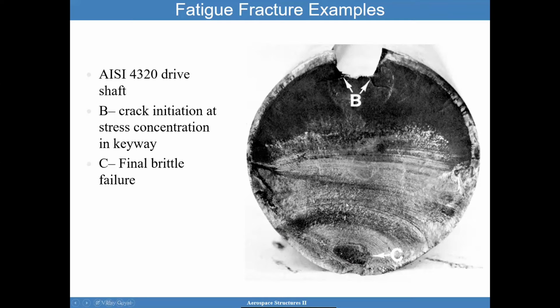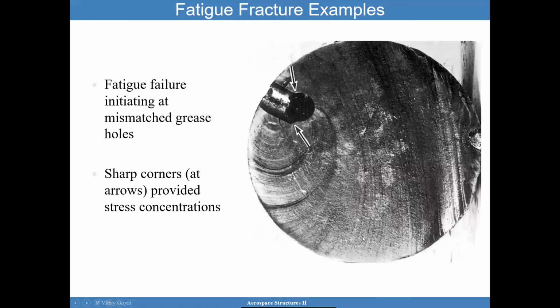But I want to point out that sometimes it's not apparent. In this example, a crack initiated at this stress concentration, propagated, and they had a final brittle failure here at the very end. You also have fatigue failures that have occurred, initiated in mismatched grease holes. So here the crack initiates from the sharp corners and then propagates until you have brittle failure at the very end.